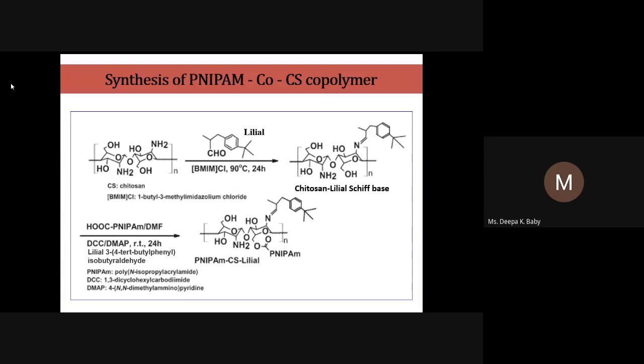Why am I choosing NIPAM? Because NIPAM is thermoresponsive. Thermoresponsive means between a temperature swing of 25 to 32 degrees Celsius, this NIPAM can change from hydrophilic to hydrophobic. Below 25 degrees Celsius, it is hydrophilic, and above 32 degrees Celsius, it is hydrophobic. We all know that our body temperature is 37. So, this NIPAM is acting as a hydrophobic moiety at 37. So that is why I had chosen NIPAM.